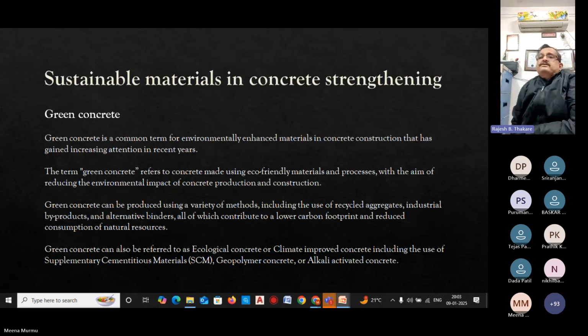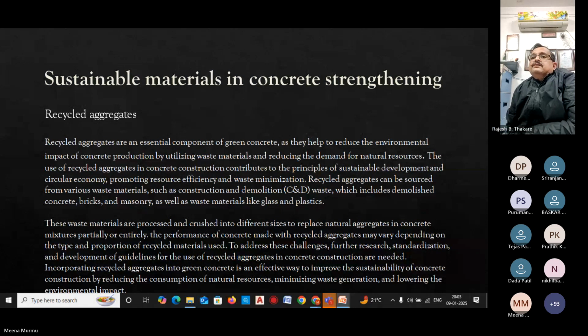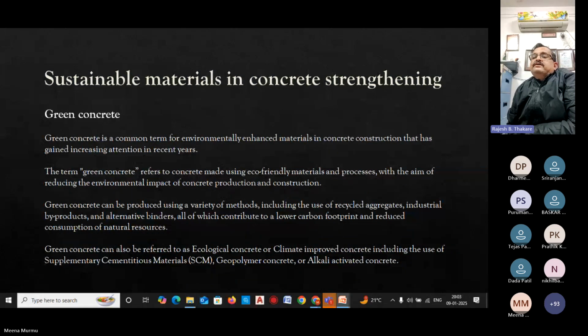Next industrial product is geopolymer concrete. It is also an eco-friendly alternative to traditional concrete, utilizing industrial byproducts such as fly ash in combination with GGBFS or other alternative binders, combined with alkali activators. So basically, geopolymers are based on alumina and silica, while alkali activated cement has a higher content of calcium.